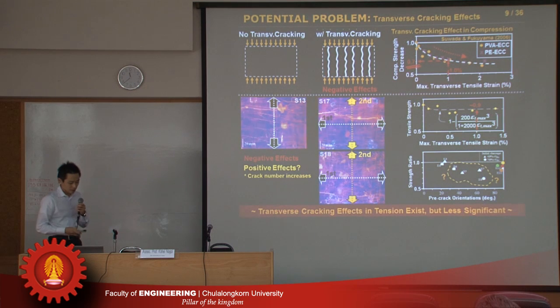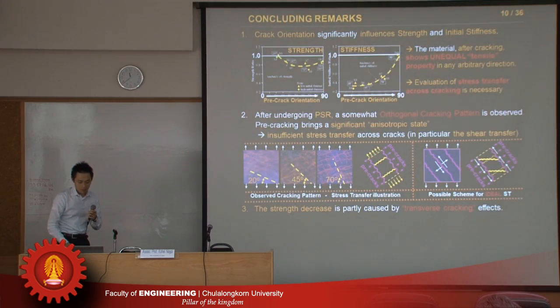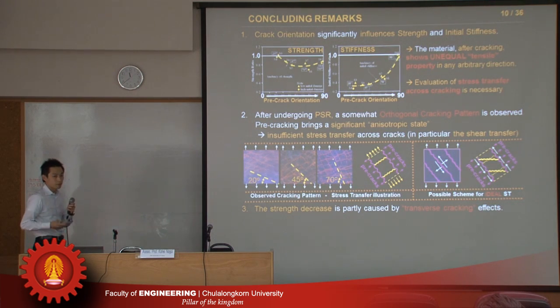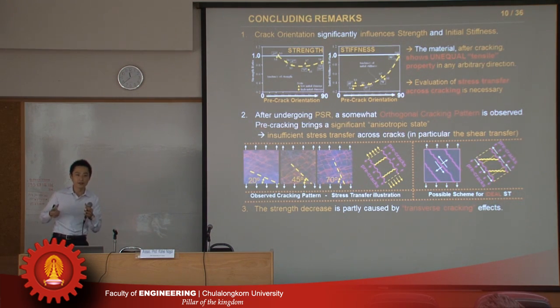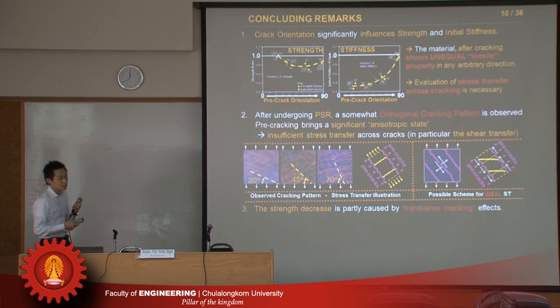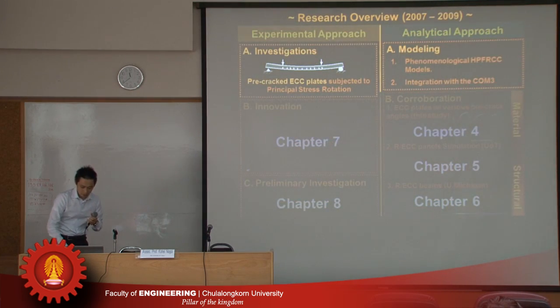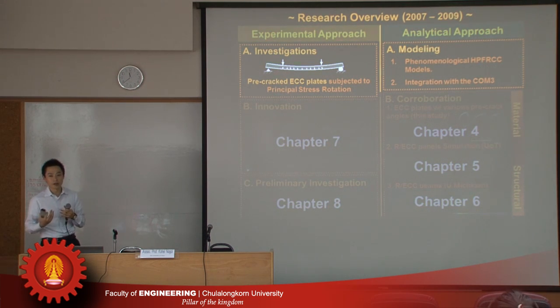So this is a cracking pattern. As we see in this case, yes, we have the orthogonal cracking when we give a 19 degrees crack. So anyway, from the newly proposed plate experiment, a very simple bending test, we could confirm the reduction of the strength due to the initial damage with a certain angle, and we could summarize. And the cracking patterns were also checked. So based on the experimental result, we try to make a model in shear.